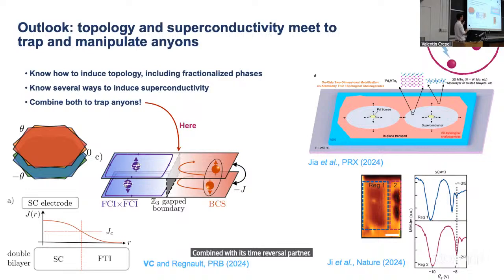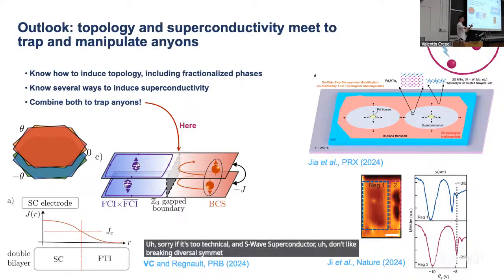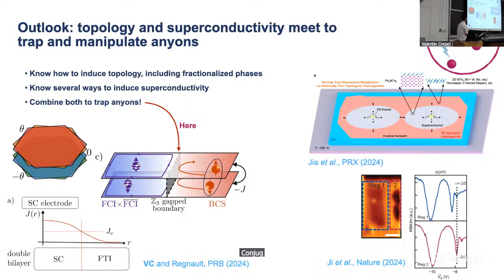There are some compatibility relations. So this phase breaks time reversal symmetry, just as if you were in a magnetic field. Sorry if it's too technical. And S-wave superconductors don't like breaking time reversal symmetry because the pairs are between Kramers conjugates. So you cannot really put them next to one another and hope anything nice will happen, because you will have a transition region where you will have an intermediate phase between the two.